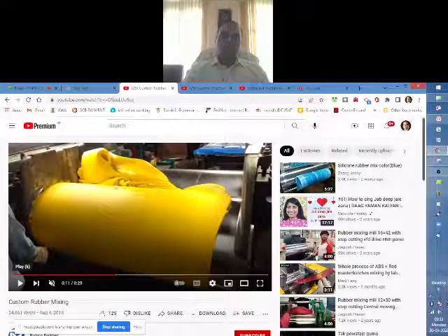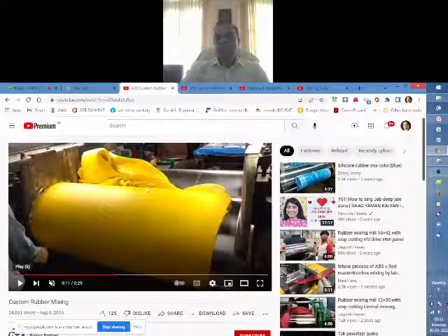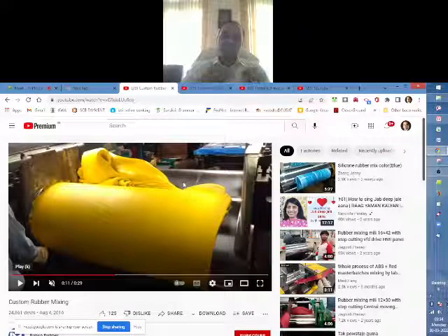See, after putting your ingredients like zinc oxide, initially when you add zinc oxide and stearic acid, when you add just the rubber there, the nip gap will be set to a slightly higher value, because the material that you put is a bigger chunk, maybe ISNR block pieces, so these are all big chunks. So the nip must be adjusted to accommodate that. Once it is compressed and the size becomes smaller, then you gradually reduce your nip.